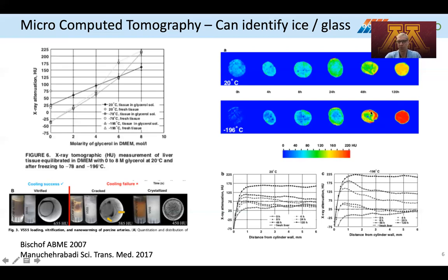So it's certainly vitrified. Here, this was given less time and less concentration. Only the edge of it is vitrified, and pretty soon you have a competition between crystallized fraction in the center and vitrified on the edge. And then these are very likely just crystallized. So this is the type of thing that you can use to assess vitrification in different systems.